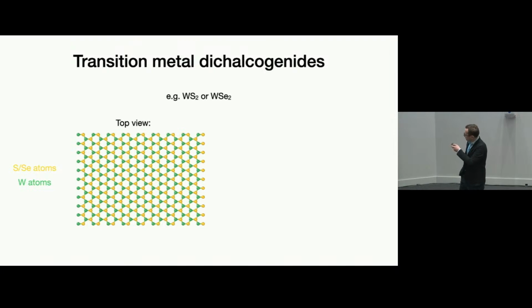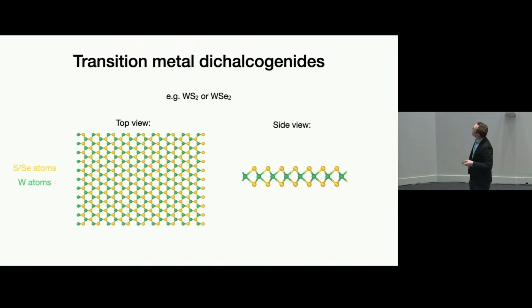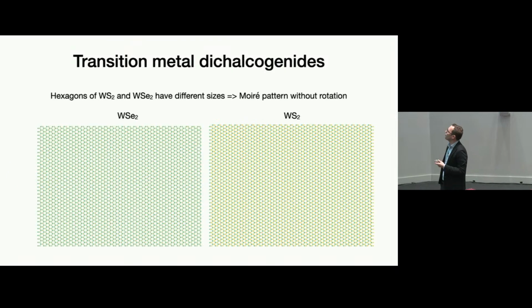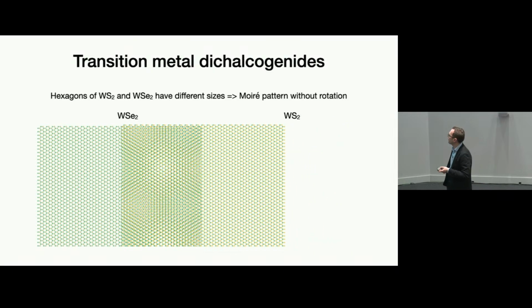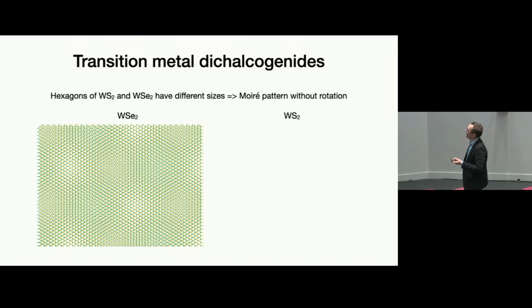So here is an example of the transition metal dichalcogenides. There's a whole class of them, for example, tungsten disulfide or tungsten diselenide. When you look at them from the top, they form hexagons like graphene, but when you look at them from the side, the atoms don't sit in a single layer, but you have the tungsten atoms in the middle and the sulfur or the selenium on the top and the bottom. Now again, you can take two of these transition metal dichalcogenides, for example, tungsten diselenide and tungsten disulfide, and you can superimpose them. You can put them on top of one another, and what would you expect? You get a Moiré pattern. And this is quite interesting because here you get the Moiré pattern without having to rotate one of the layers.